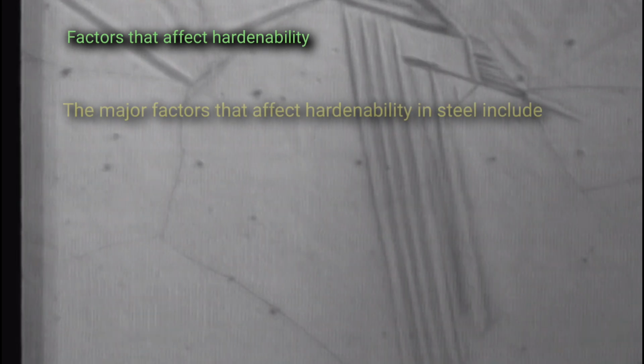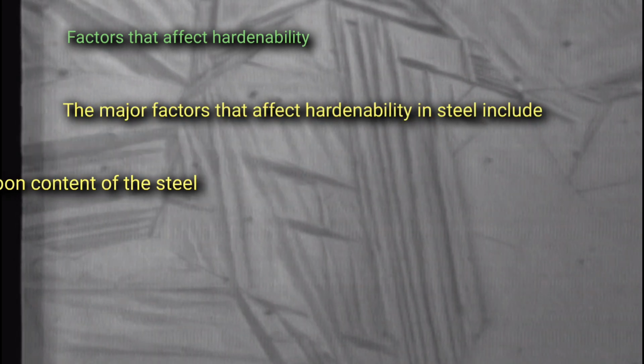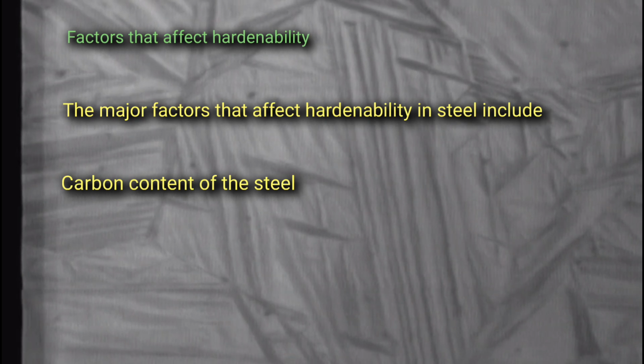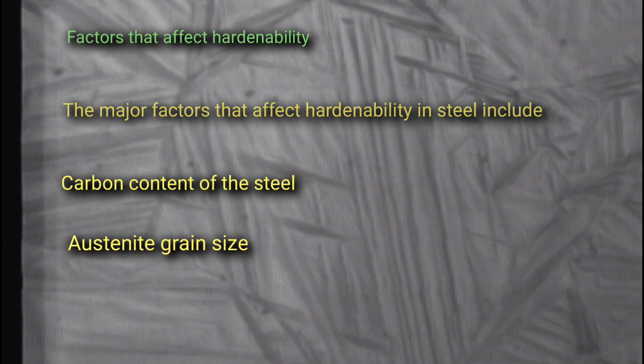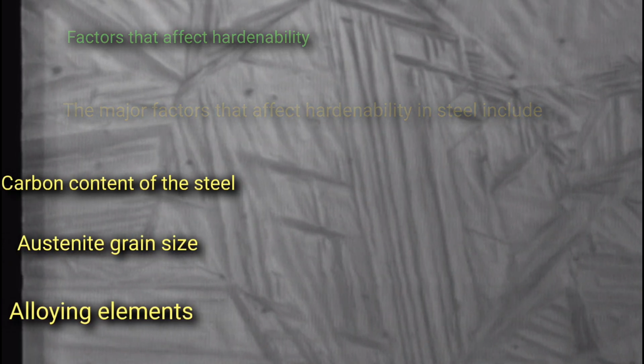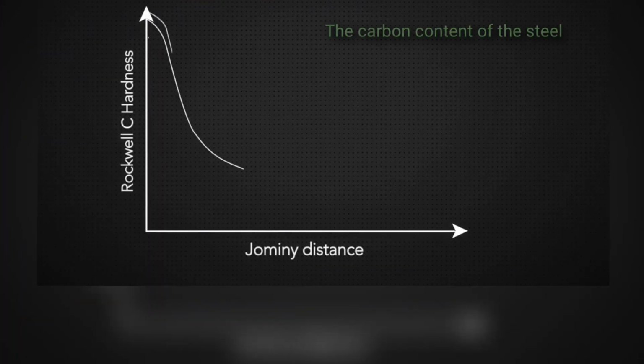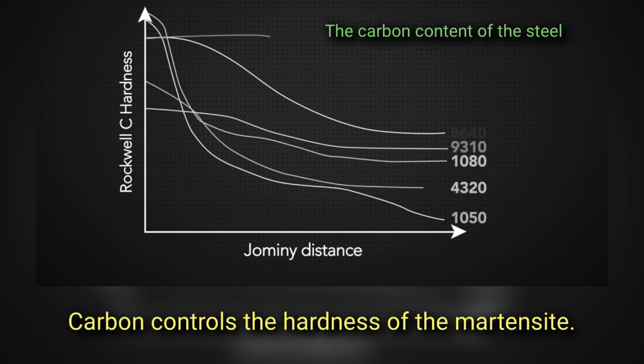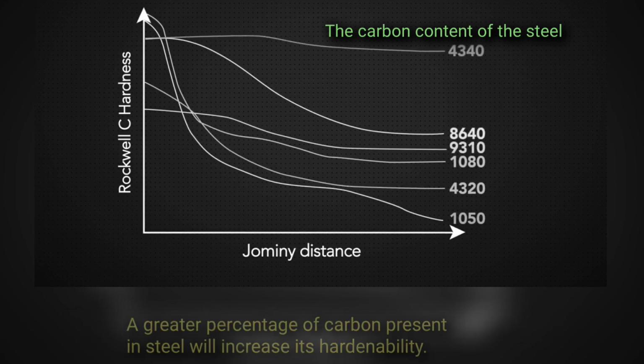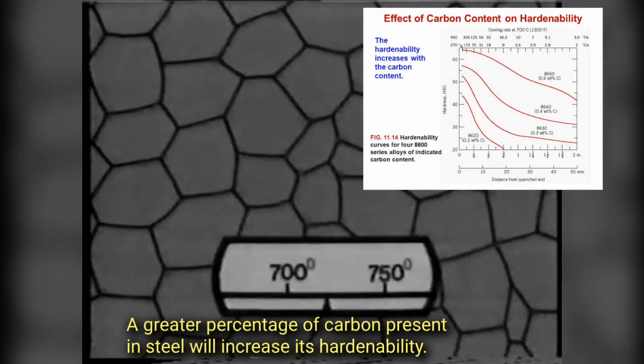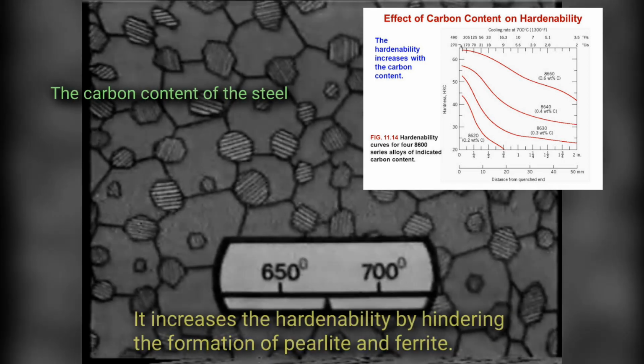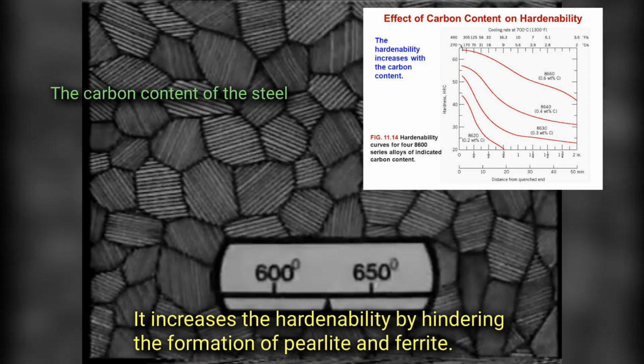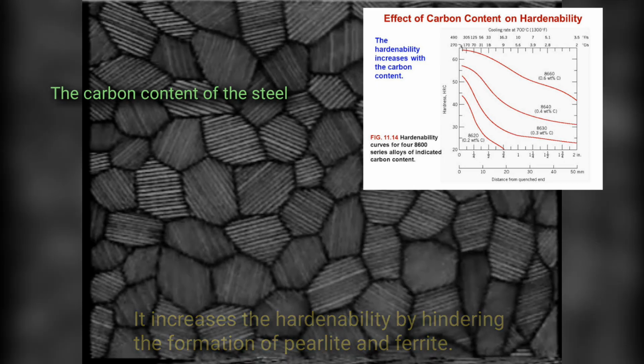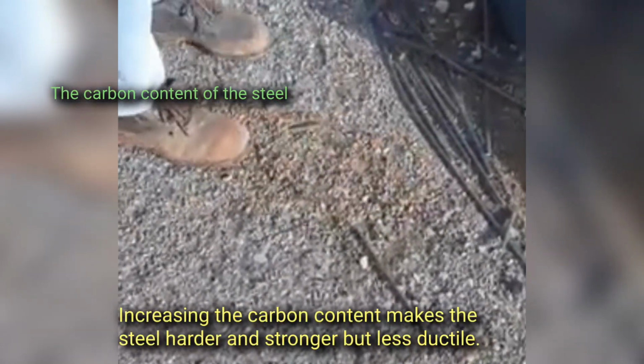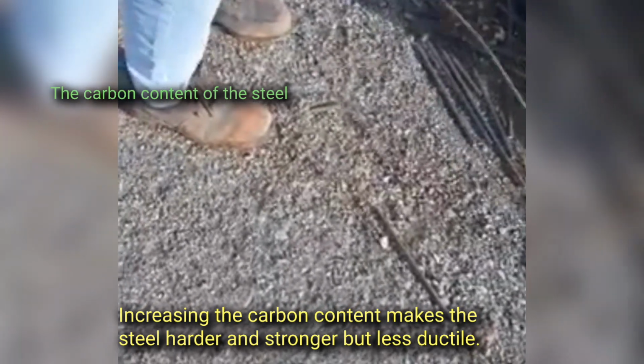Factors that affect hardenability. The major factors that affect hardenability in steel include: 1. Carbon content of the steel. 2. Austenite grain size. 3. Alloying elements. The carbon content of the steel: carbon controls the hardness of the martensite. A greater percentage of carbon present in steel will increase its hardenability. It increases the hardenability by hindering the formation of pearlite and ferrite. Increasing the carbon content makes the steel harder and stronger but less ductile.